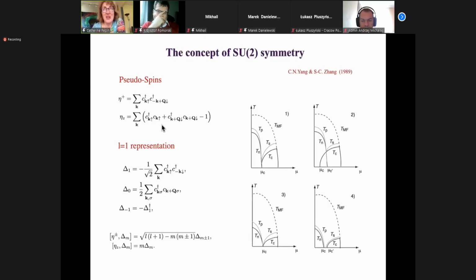And then for Christoph, this is a pseudo-spin. So basically, it will behave like a spin. But this is less robust than a spin. This is a topological concept, and it has a chirality, nonlinear sigma model. The topological defect can be protected from disorder. They will be very resistant to disorder, but this is always a bit less. You see, the constraint is emergent. It's not as robust as nature provides you a spin. Then, I mean, the constraint on the fluctuations on the 3 axis of the spin operator is very strong. Stronger than this one.